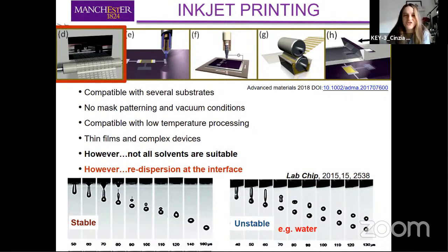However, inkjet printing is actually not as simple as it looks. There are two issues that we need to remember when applying inkjet printing to the fabrication of heterostructures. The first issue is general issues related to the inkjet printing technique itself. Many of the printers that you will find in the labs are piezoelectric inkjet printers. And in this specific case, not all the inks will be inkjet printable. The inks must have specific rheological properties. This is because the rheology, so surface tension and viscosity of the ink, basically determine how the droplet is formed at the nozzle. And in turn, this determines how well the material is deposited on the surface.